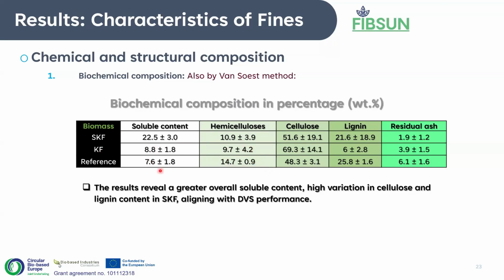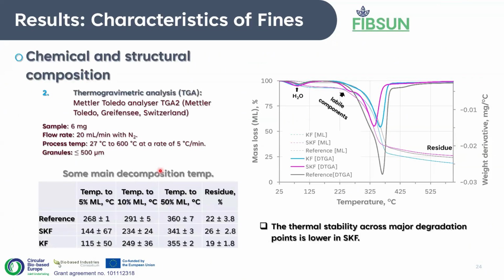So furthermore, we then examine this chemical structure and composition with thermogravimetric analysis. And this gives us an idea of the thermal stability of the material. And we see correlation between what we already observed in terms of chemical composition and with a reference.